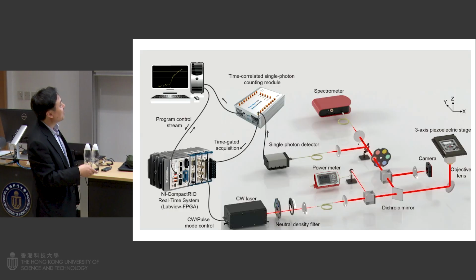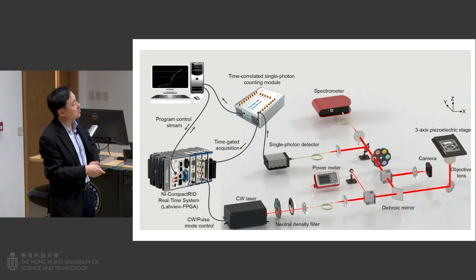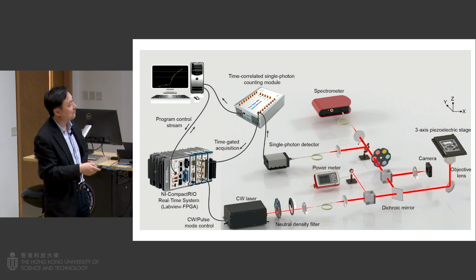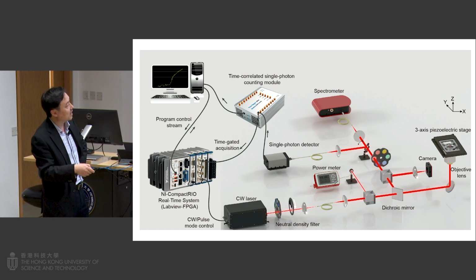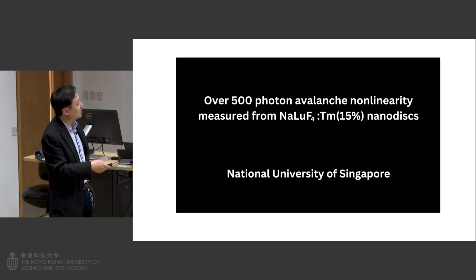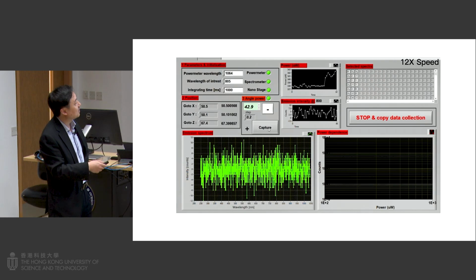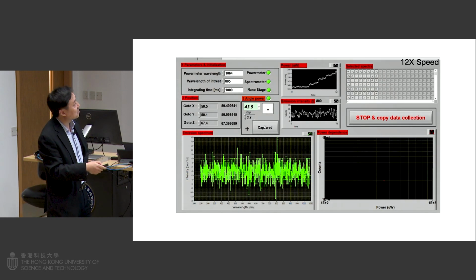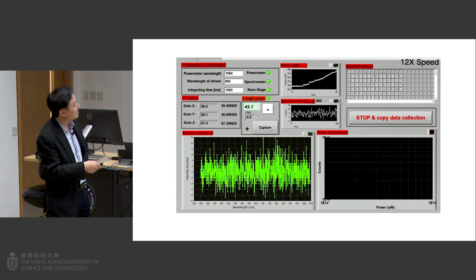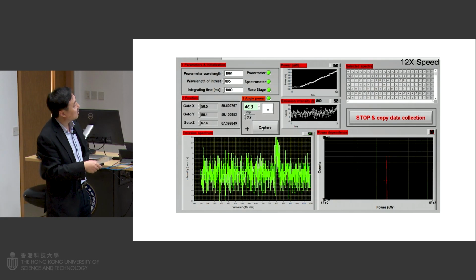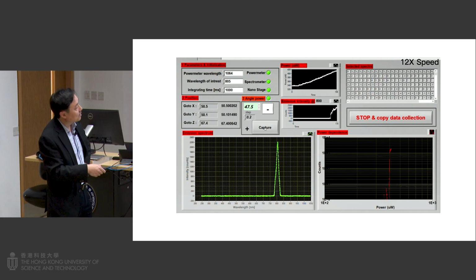Yeah. So I want to show the optical setup, which is actually very straightforward. It's nothing fancy. You're using several optical components, and you can achieve that. Most important is to synchronize the measurement of the power density and the emission intensities using this spectrophotometer here. I just want to quickly show you. Let me see. Okay, so here I sped up the measurement. You can see we keep increasing the excitation intensity. Then suddenly, once we reach the threshold,